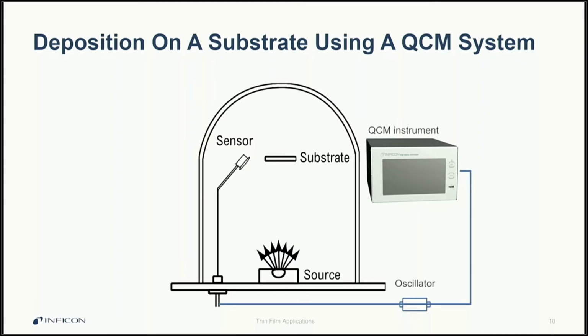In this example, we physically heat up the source until the material in the source either evaporates or sublimes. The newly gaseous material then expands to coat all of the cooled surfaces in the chamber. And then after the deposition is complete, you can see that a thin film has been deposited on both the substrate and the QCM, as shown by the blue marks on those two parts.